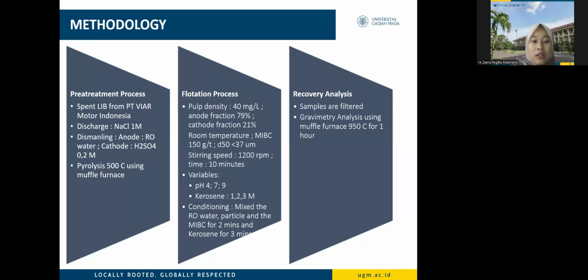A pH adjuster, sulfuric acid, was added to achieve the set variation conditions at pH 4, 7, and 9. The flotation process was held for 10 minutes with an MIBC dosage of 150 grams per tonne at room temperature. The sample collected for 10 minutes as the top result was tested using the gravimetric method by inserting the sample into a muffle furnace at a temperature of 950 degrees for 1 hour. The remaining sample was weighed to obtain the anode and cathode recovery values.